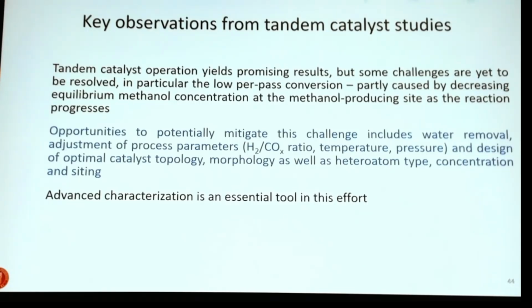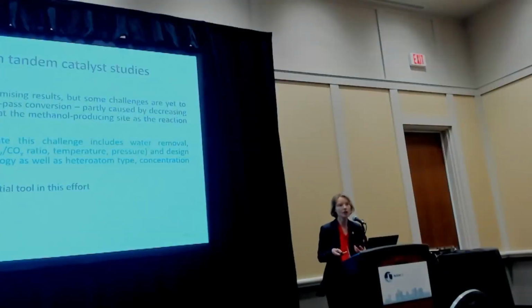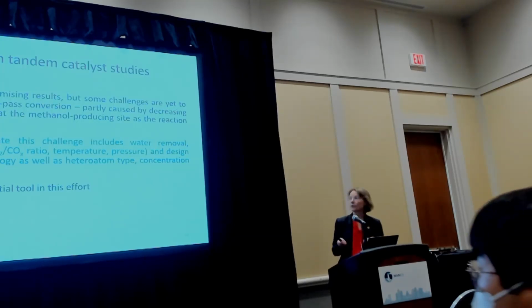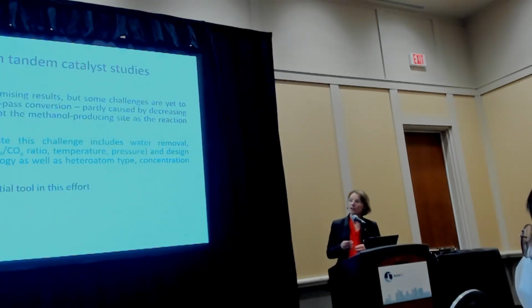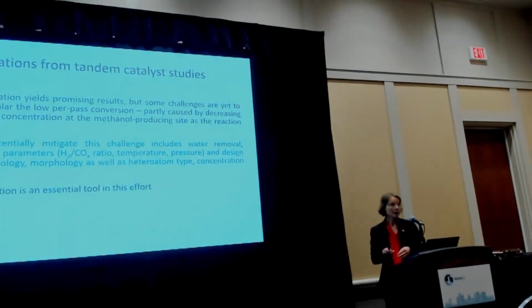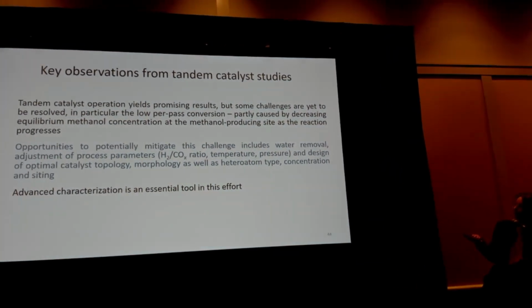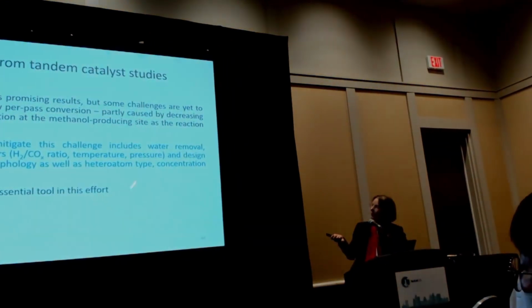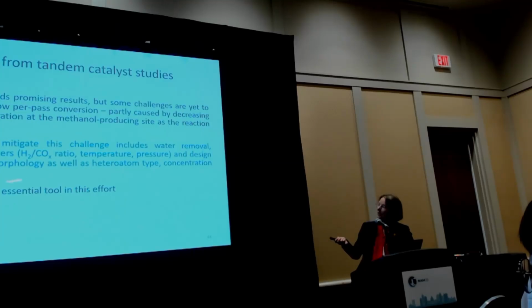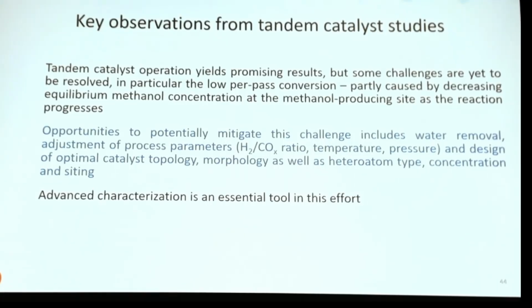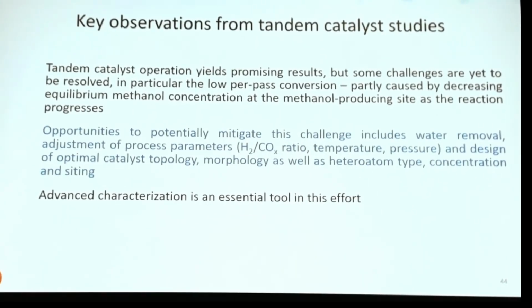In conclusion of these studies, we see that the tandem operation of catalysts from CO2 directly to hydrocarbons via oxygenates shows promise. But we see that the per pass conversion is quite low. So that has impact for the process, of course. And then we have these potential opportunities to mitigate this challenge. And we see that in order to design the correct material for this process, advanced characterization is essential.